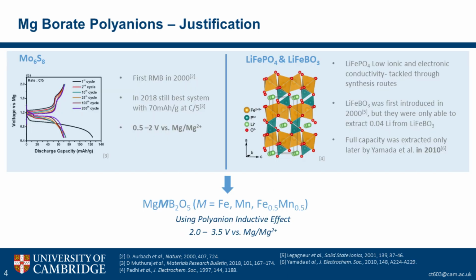So my work focuses on developing a cathode material to improve on the operating voltage of the Chevrel phase. And what we did was we took inspiration from lithium iron phosphate, which has had a lot of commercial success in recent years, and the lithium iron borate species, which isn't yet used commercially, but has shown really good capacity improvements in the last couple of decades.